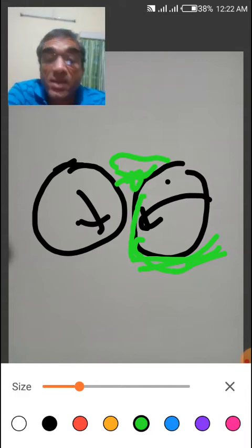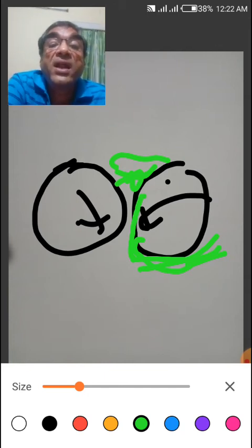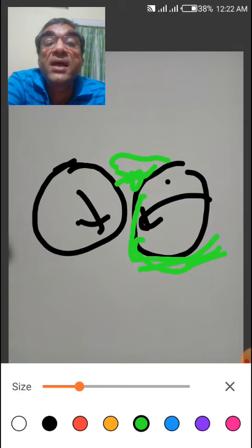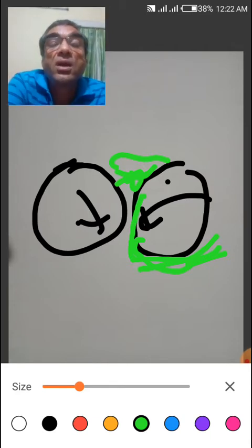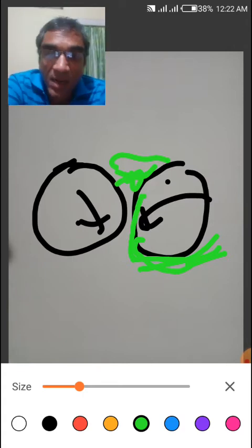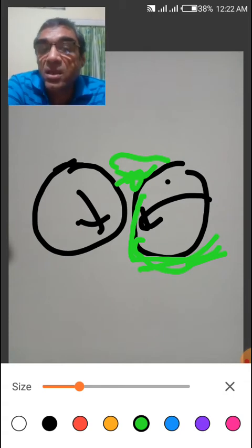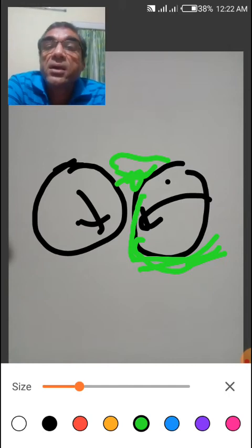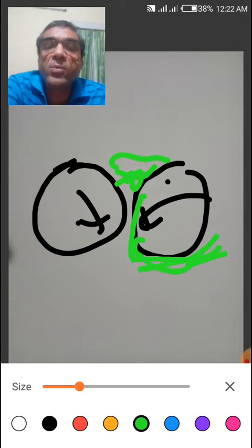Now you may ask, and you should ask, why this blend, which has been made using a two roll mill, has stuck to this roll only. See students, this might have stuck to that also. This we can control. To which roll your melt will stick can be controlled. How? By varying either the temperature, we will keep the temperature of this roll a bit high, or by changing the speed, we will keep the speed of this roll a bit higher than the other roll, or both.